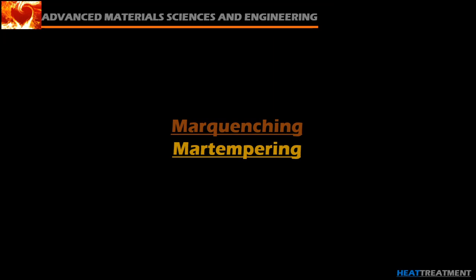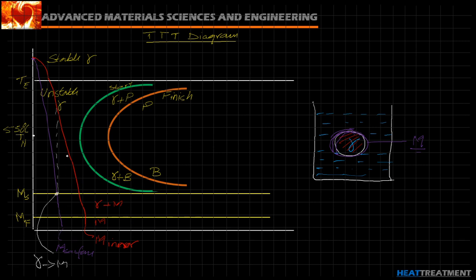As we have seen, the residual stresses are produced as the component size is large and the inside austenite is still warm, but the outside surface austenite is cooled and transformed to martensite, as shown by these two curves. Here this purple shows the outside temperature that is cooled down to the complete transformation of the martensite. At this temperature, still the inside component is austenite.